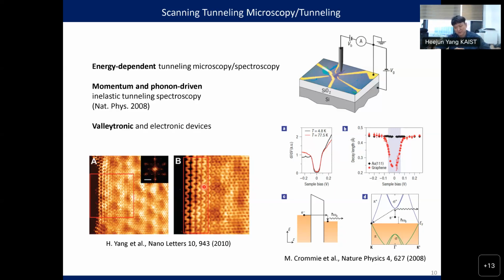What about momentum-dependent transport, as I mentioned in my first slide? In my opinion, one pioneering example is this one. When we study graphene by STM, we have to make tunneling current vertically from the tip to the graphene. So the tunneling electrons are moving vertically. But once the electrons enter the graphene, they should flow in plane. Momentum should be in plane. So from the gamma point to the K point, we need a sort of momentum change, and this is called inelastic scattering. Then inelastic scattering takes place, and we can see it as a sort of bandgap-like feature. So in my understanding, this is one of the first examples to show the momentum effect in transport. But we can develop this idea further to use this new degree of freedom in our device operation.